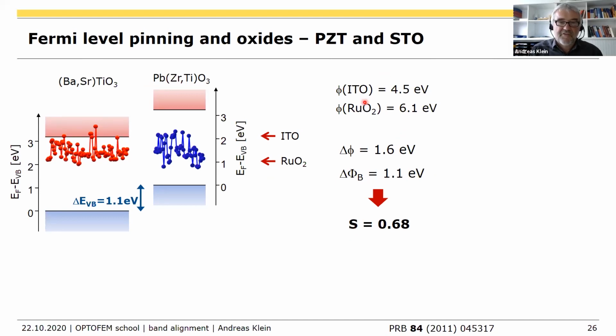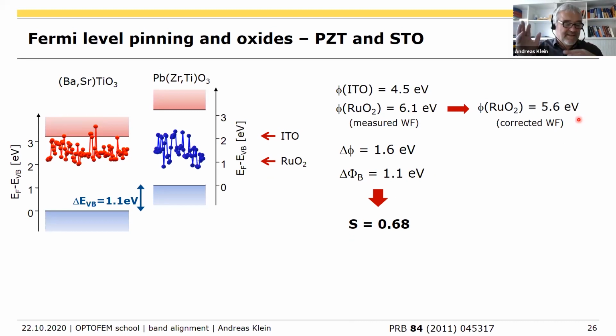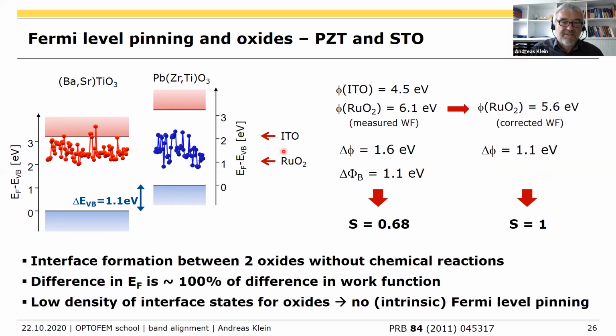But this was one of our first experiments with ruthenium oxide, and we did many, many after that. And we learned that ruthenium oxide doesn't behave at the contacts like it has a work function of 6.1 eV, it behaves more like it has a work function of 5.6 eV. So the measured work function is a difficult thing. This is like for the ionization potentials of the semiconductors. If we take this one, the difference in work function is 1.1 eV and the difference in barrier height is 1.1 eV. So there is no pinning at all. So that means we can move the Fermi level around at the interface if we just get proper materials. And it's important that we use oxides because they don't make a chemical interface reaction. Okay. And it's clear that we have no Fermi level pinning for these kind of materials at the interface, if you are careful not to introduce defects by how you make your interface.